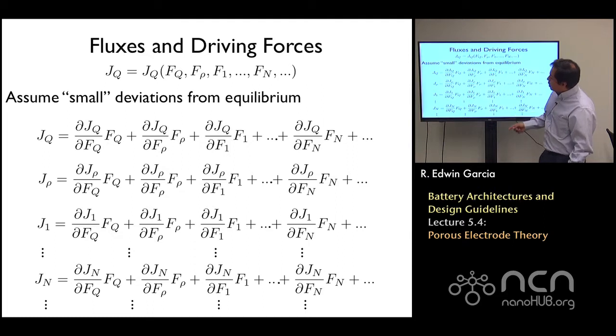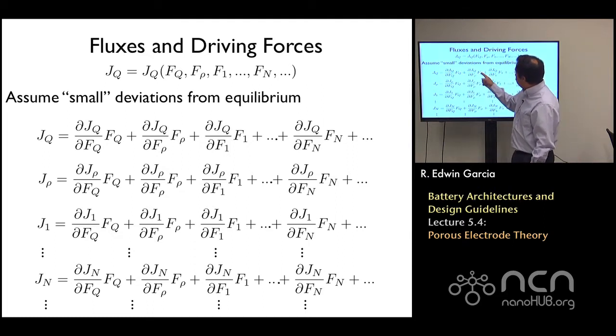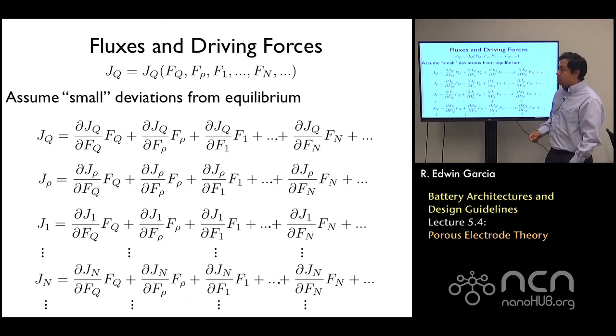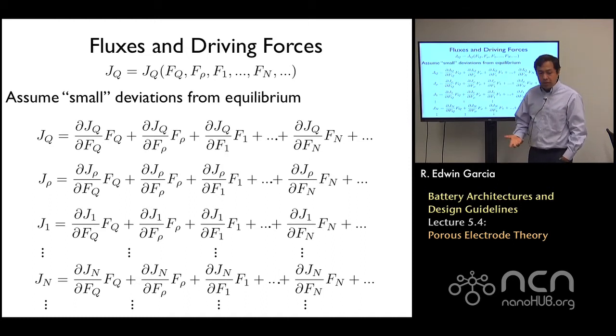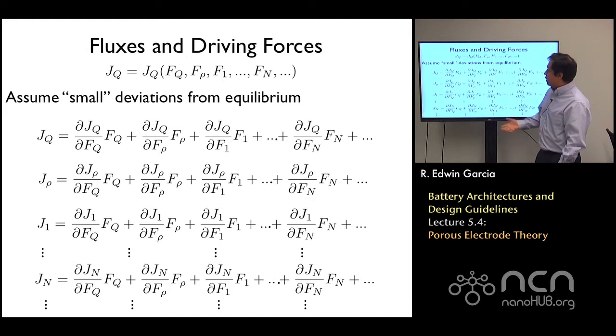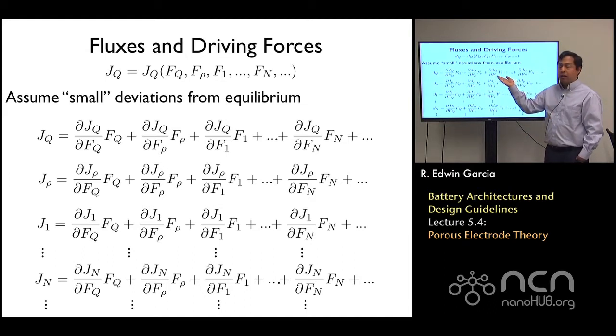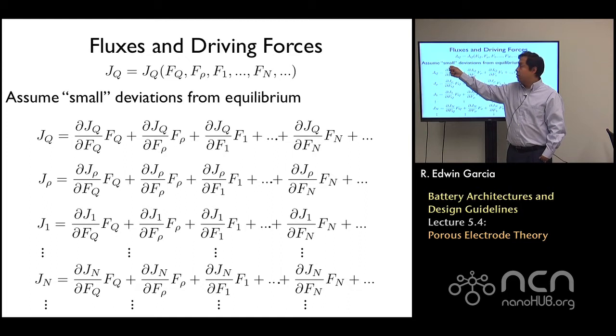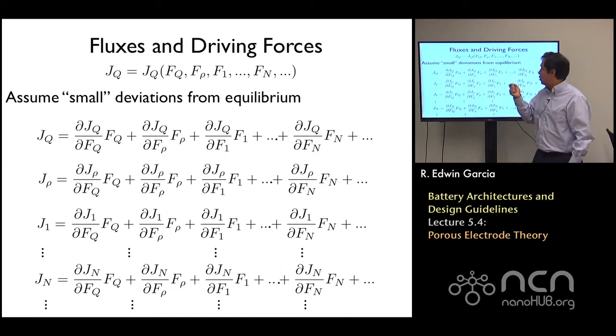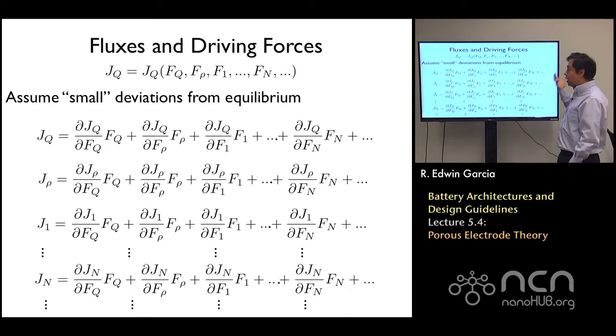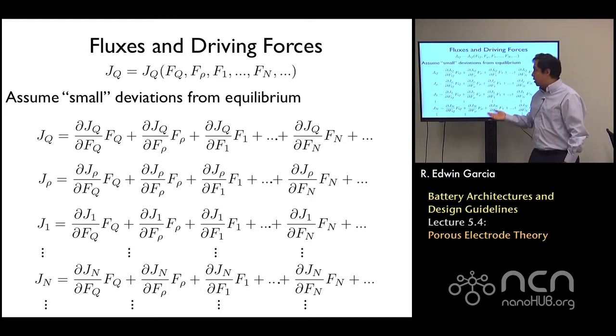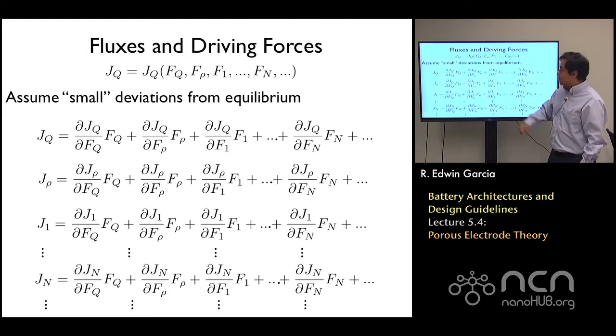and in this case it boils down to the identification of what each of these coefficients, these partial derivatives, means. There are some rules, a very well specified set of rules as to what controls it, but as you can see, it all depends on what the linear driving forces specify the control of it. And here the key word is that we are performing small deviations with respect to the equilibrium value. Okay, if we had large deviations, then we would not only have to put the linear terms, but we would have to include the quadratic, cubic, higher order contributions to the flux of the system. But in the limit of small deviations, then we can think of these combinations.